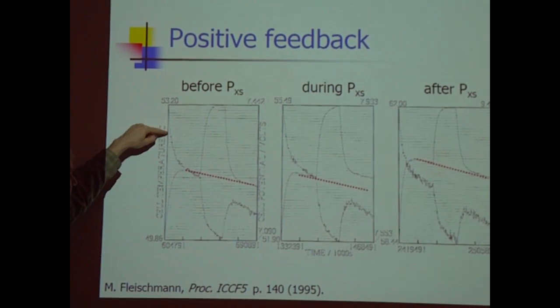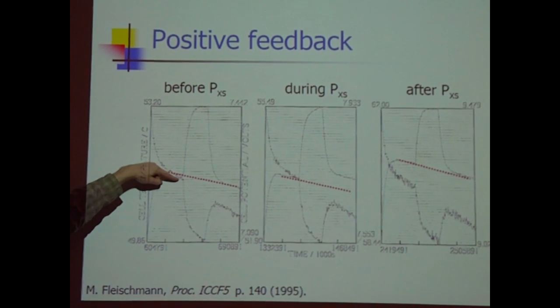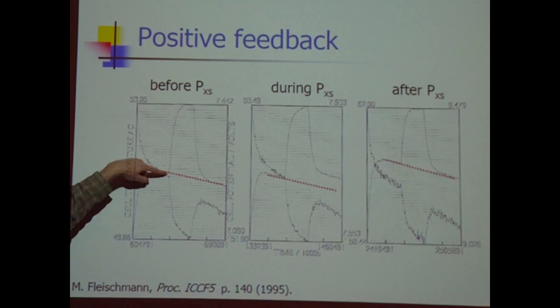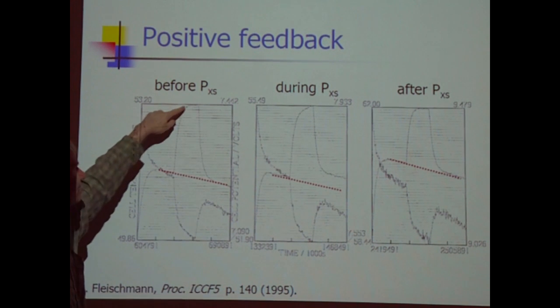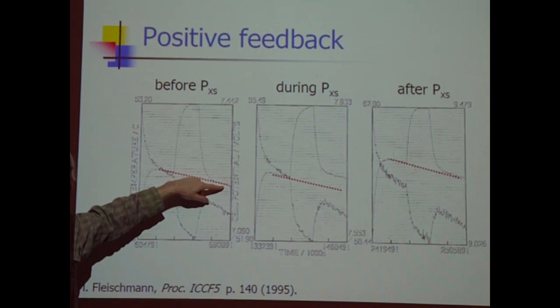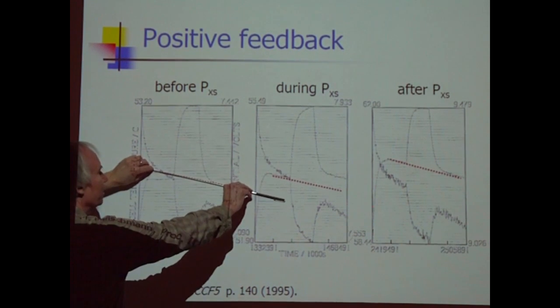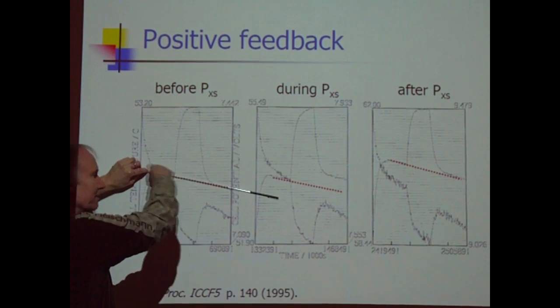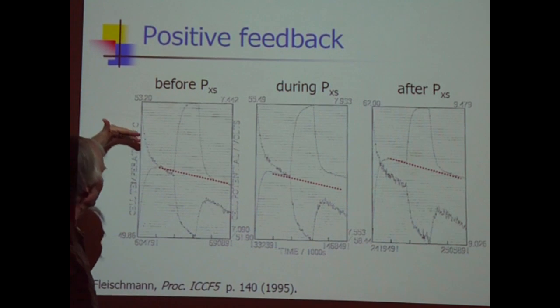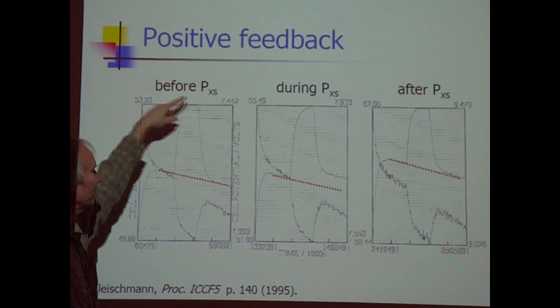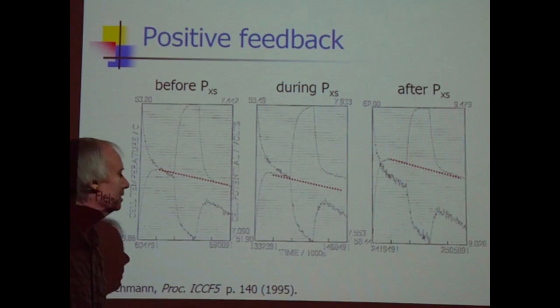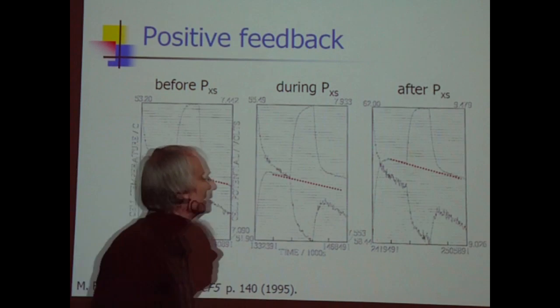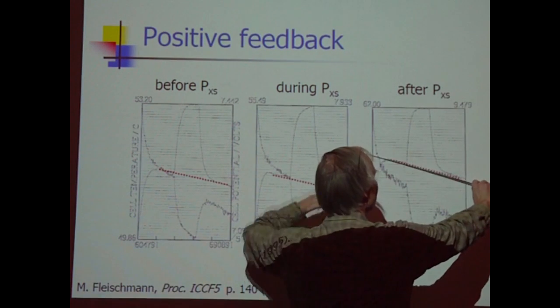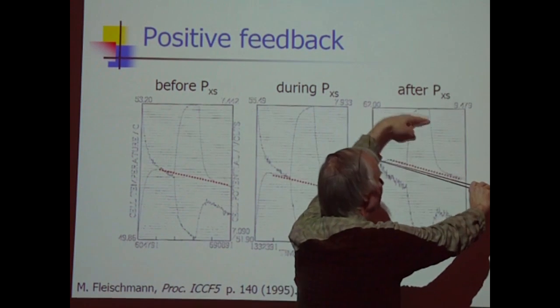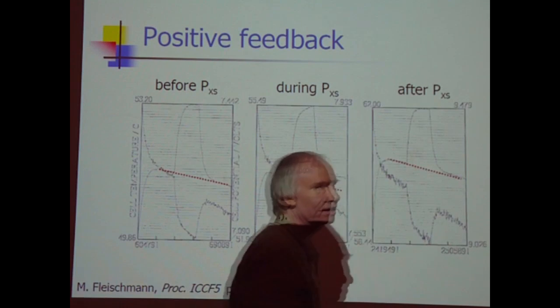So I'm looking here at the temperature profile in the case of a calibration pulse. So here's the temperature rising during the calibration pulse. Temperature comes back down. And if you think about it, the calibration pulse is an increment over something larger that the cell is doing. So the cell, in this particular case, cell temperature is dropping. Calibration pulse happens, but it doesn't impact the dropping of the cell temperature. So this is done before an excess heat burst. After an excess heat burst, the same kind of thing is observed: temperature is coasting down, calibration pulse, the temperature relaxes back to where it was coasting down.